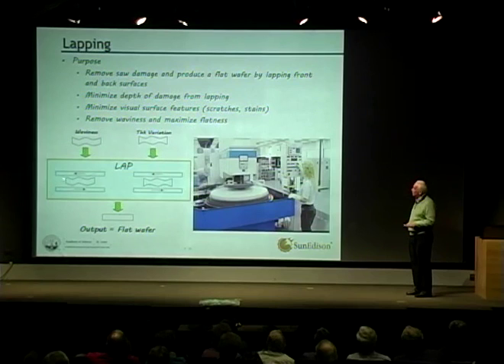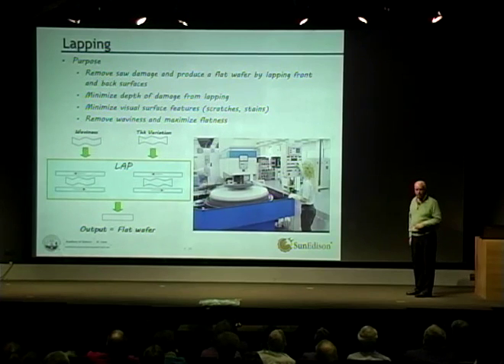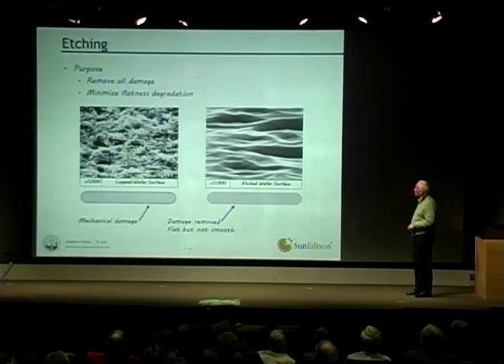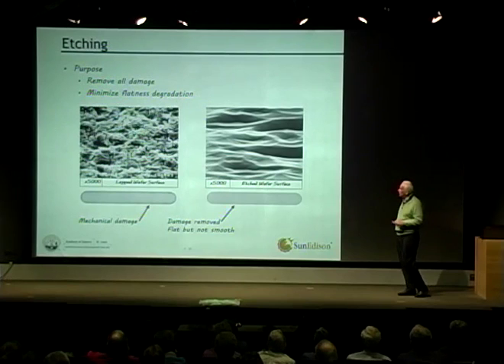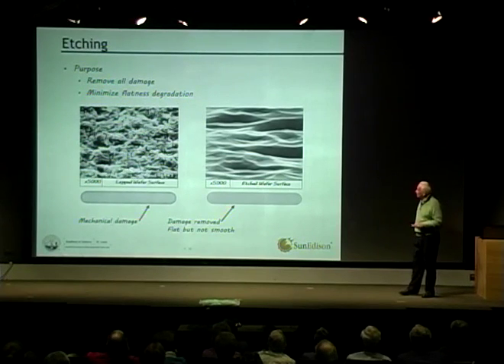We may have a wafer that looks like this, where we've got what we call waviness, where the thickness is the same, but it's wavy. And here, the thickness is varying. We call this thickness variation. When you lap it, it comes out flat. And this is about as flat as the wafer gets in the operation. It's flat, but it's not smooth. It looks like this. This is very similar to a sliced wafer that comes off the saw. It's very similar to this, except the depth of the damage is a little bit less. And so it's represented here.